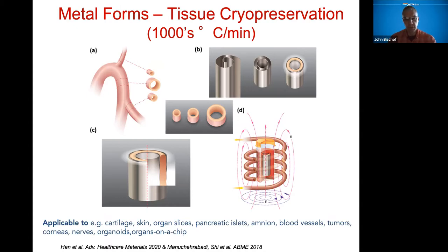Arteries that are 1 millimeter thick or less had been preserved since the early 2000s, maybe even the late 90s, by a variety of different groups around the globe. But nobody had really done these really thick systems. And so in order to address this, we used basically glorified aluminum foil that we wrap on the inside and the outside of these thicker arteries. And after they've been appropriately loaded with cryoprotective agent, we can then rewarm them at thousands of C per minute.